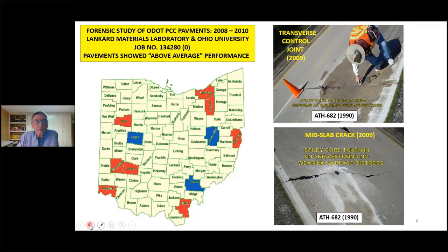The study that I mentioned, in 2008, 2010, I was involved in with Ohio University. I'll actually identify those publications that you'll have an opportunity to see. We looked at 20 different PCC pavements in 11 different counties around the state. And the pavements were selected on the basis of having shown above average performance, trying to see what was done right back then. However, it was recognized that the joints and the slab cracking and distress were a major part of the problems, even with those. So all of the cores that we looked at were taken through the joints and through the cracks, and we took them in a region that was not yet showing distress in the wearing surface.